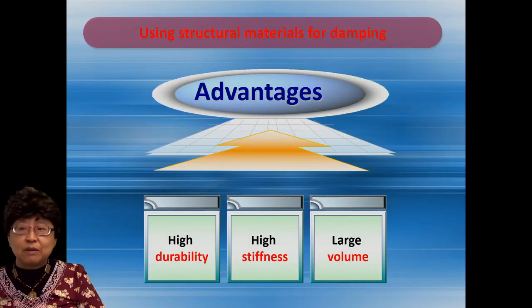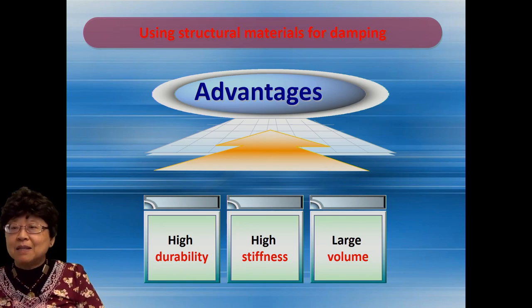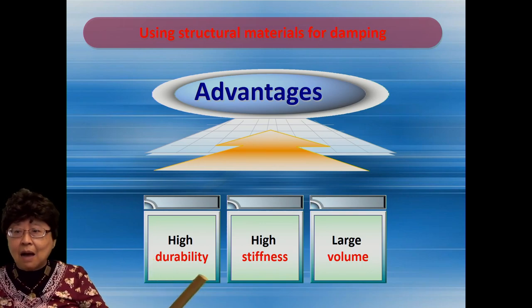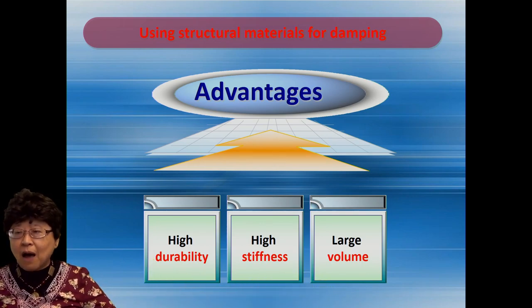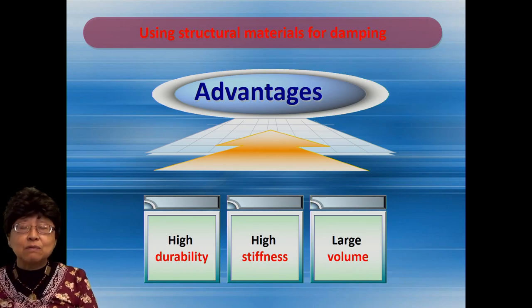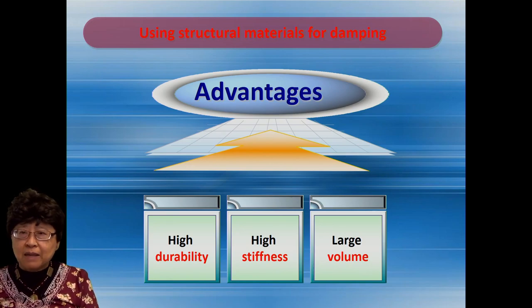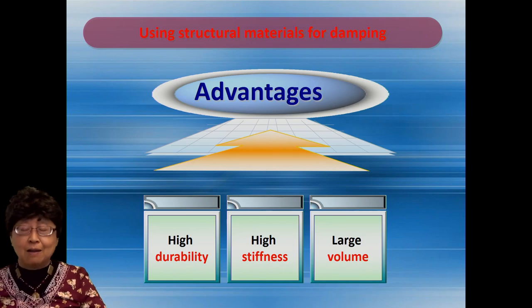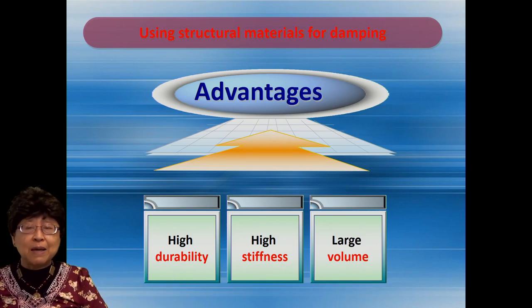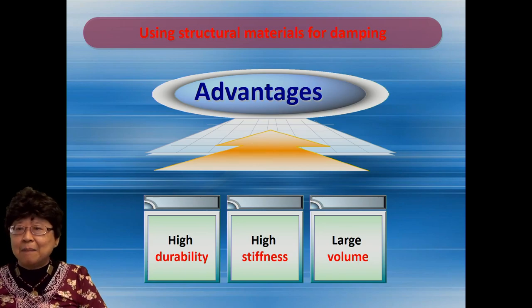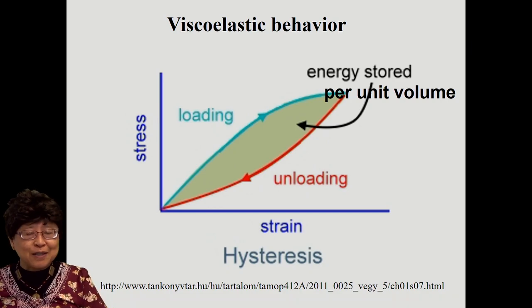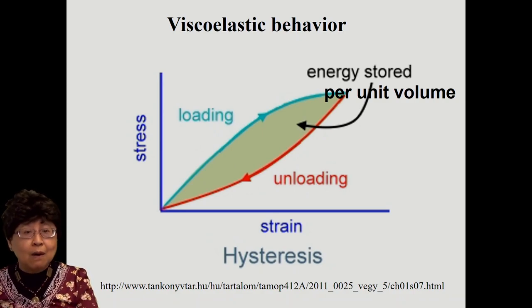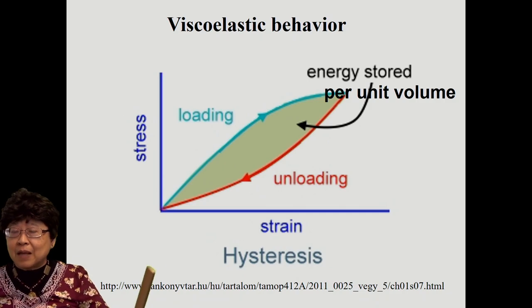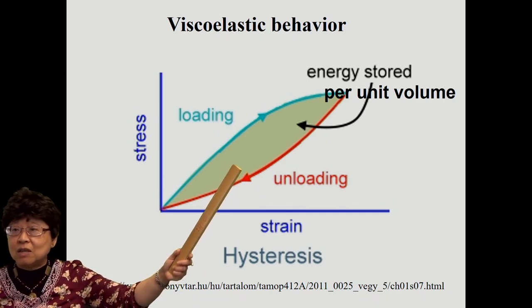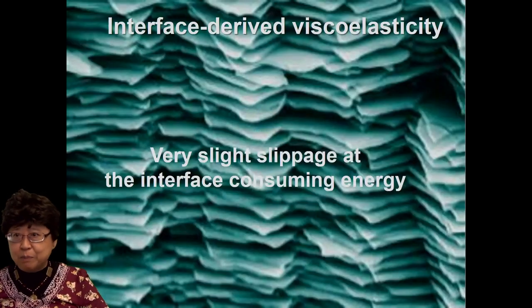However, using structural materials for damping, that's revolutionary, and it has advantages: high durability, high stiffness, and large volume. The volume matters because the area of the hysteresis loop corresponds to the amount of energy dissipated per unit volume. So if you have a large volume for the structure, you would be able to dissipate a lot of energy. Okay. But this is revolutionary. People have not even dreamed about using a structural material which is stiff for vibration damping. And I explained already that this is energy per unit volume, so using a big structure helps.